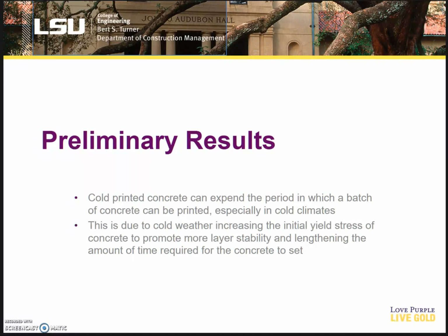So, preliminary results. Cold printed concrete can expand the period in which a batch of concrete can be printed, especially in cold temperatures. This is due to cold weather increasing the initial yield stress of concrete to promote more layer stability and lengthen the amount of time required for the concrete to set.